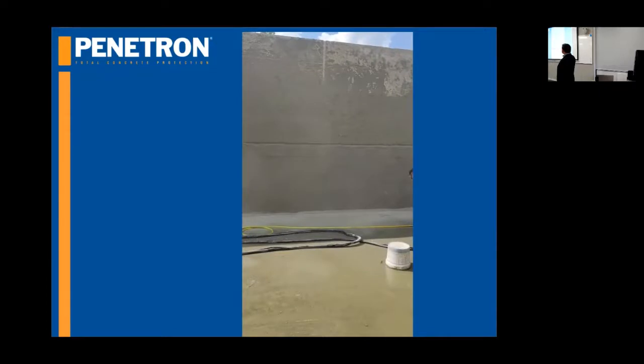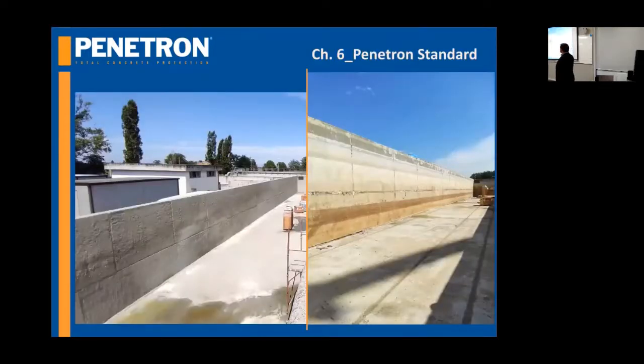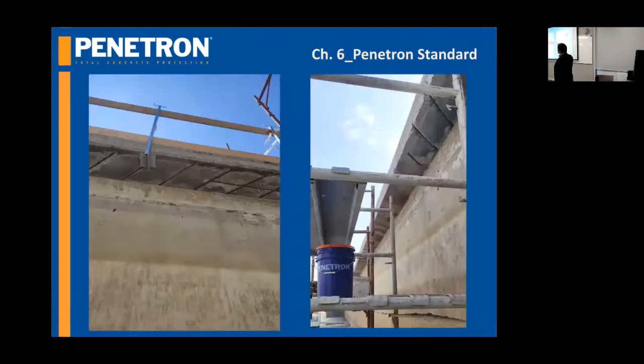These are joints that had been cured before, movement joints, because it's a very big tank. So we use an elastic paste, and then we could apply it. This is the result before and after. And this is how we repair the damaged part. You can see from this side, these are the continuations of the work.